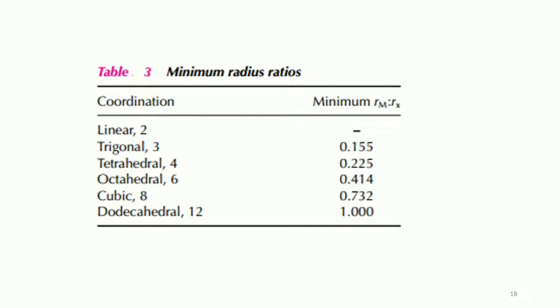The radius ratio rules are successful in predicting trends in coordination number and structure type, but can be used only as a qualitative guide. Radius ratios depend very much on which table of ionic radii is consulted, and there appears to be no clear advantage in using either one of the more traditional sets or the modern set of values based on single crystal X-ray diffraction results.